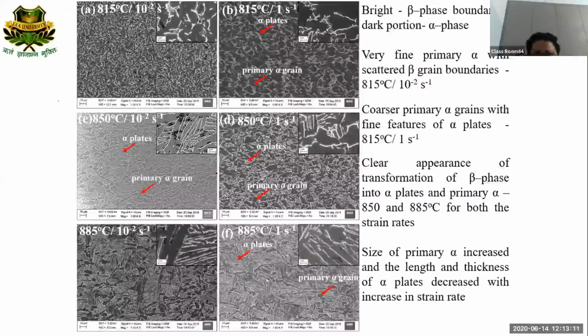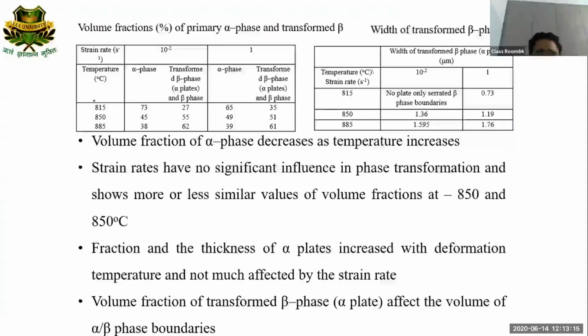Okay. So some quantitative analysis of the volume fraction of alpha phase and beta phase was done and is shown here. Then we can say that at 815 the alpha phase is 73%, and gradually as you increase the temperature and approach the beta phase, the alpha phase fraction is reducing in all the cases. But the transformed beta phase is increasing. Transformed beta means alpha plates. So if we measure the width of these alpha plates or beta plates, we can see that it is increasing a little bit as we move towards the beta phase.